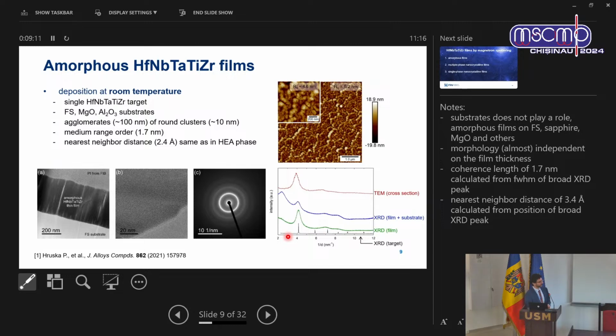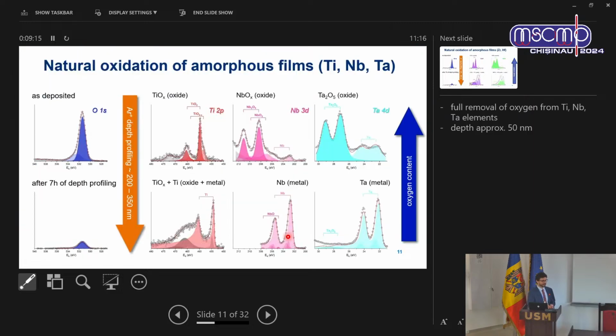Also, those elements like hafnium, zirconium, and so on are really sensitive to ambient oxidation, which is very nicely visible in the XPS results. Here in the top line, you can always see the state of as-deposited films with dominant oxide peaks. And to remove this oxide layer from the amorphous films, we had to profile it by argon sputtering for about 7 hours to remove 200 to 300 nanometers of the top layer to finally uncover these metallic elements. At least in the case of titanium, niobium, tantalum, we really reduced it to the metallic. In the case of zirconium, hafnium, there was still some signal from oxide, so it really oxidizes deeply into the material.